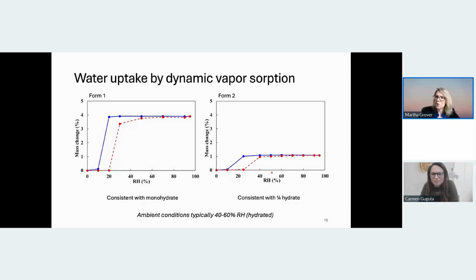But we're not ruling out that it could actually be stoichiometric, loosely bound water in the channels that is easily removed. And actually, this water is also easily removed, right? They're both at ambient conditions. But somehow form 2 takes up only a quarter of the water. And I don't think we see really dramatic changes in the XRD between form 1A and form 2. I think there are some differences, but at the same time they could have some structural similarities. But also some differences because of the solvent that was present during crystallization. Yeah, indeed. And you had confirmation from the multiple XRPDs, X-ray powder diffractions, that there was no real structural change in form 2.